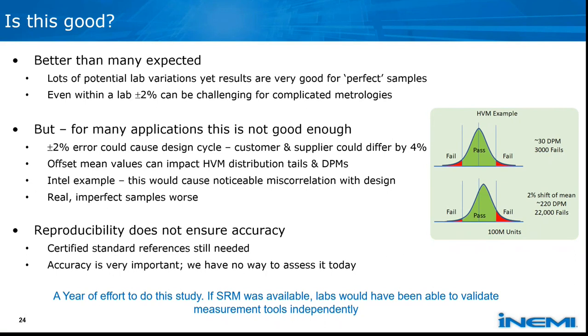So there are reasons why we, as an industry, should be able to do better than this kind of tolerance. And again, we're looking at perfect samples, so imperfect samples that are realistic material samples for substrate materials are going to provide more variability. I also want to note that the reproducibility we've been talking about here really doesn't ensure accuracy. This is important, because if we had certified standard references, we would have an accuracy assessment—in other words, we could assess how accurate our final result is, as opposed to just what the reproducibility is.